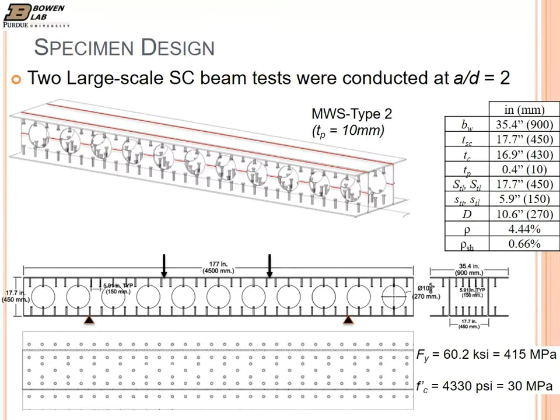This is the second specimen. This time we have the web plates in the longitudinal direction, and I'm also indicating the weld locations on the top. For this specimen, we had twice the width of the previous specimen because we have this core region in between the web plates and the top face plate. So we wanted to capture the confinement effect in that region, and we went with two unit widths instead of one unit width. Other than that, most of the parameters were similar to the first specimen. So the width was 900, but the rest of the parameters were again comparable with the previous specimen. We tested again at 2.0, and the material properties were similar to what we had for the first specimen.